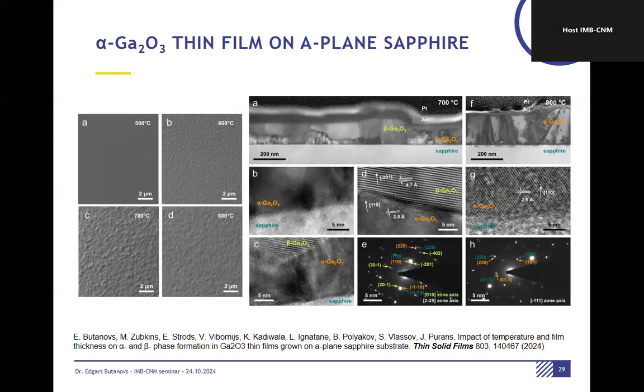Let's take a look here. So at 700 degrees, what we obtain is some islands of alpha phase nucleation. And then when you have some exposed facets of other orientation, not the favorable one for alpha phase growth, the beta phase grows, probably away from these exposed edges. However, when we increase the temperature, we can see that we only have alpha phase growth up to some nice thickness. Here it's nearly 300 nanometers thick.